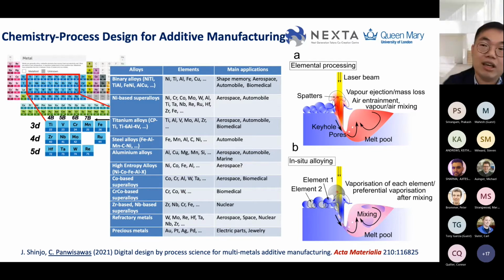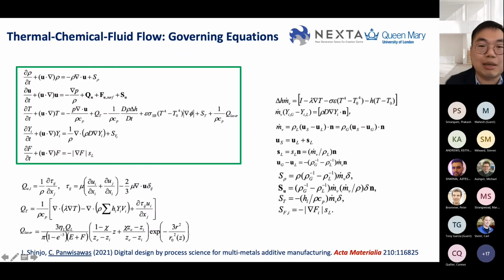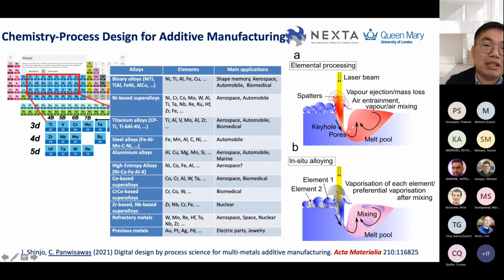Or moreover, we can improve some properties using this technique for current additive manufacturing applications. For example, in the biomedical application, when you have a binary nickel titanium system, the nickel actually is lost a lot compared with titanium, and then you have to understand how it happens and how we can compensate for the percentage lost by the process condition. So this is the ultimate goal of working on this. But we want to generalize this into the whole 3D, 4D, 5D transition metals, and then select some materials which are available in the aerospace, automotive, and biomedical areas.